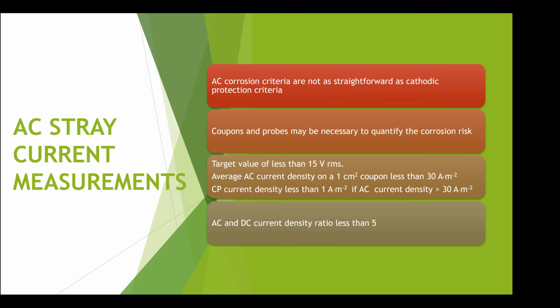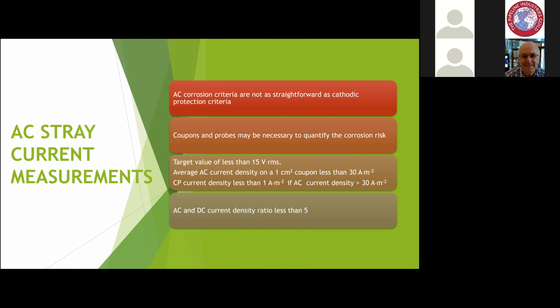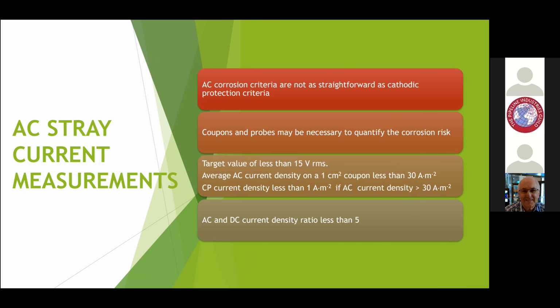And we use something called a coupon, which is just a piece of steel with known characteristics, with a known surface area, and sometimes with a known thickness. And what we know from all of the scientific work and practical work that's been done is that a surface area of 1 centimeter square is the standard that we use for assessing the risks. It can't be scaled up. You can't say that 30 amps per meter square is okay on 1 centimeter square, and you could have 60 amps per meter square on a 2 centimeter coupon. It doesn't work like that for various reasons. So within the standards, we've standardized on a 1 centimeter square coupon to do all the evaluation of the risks.